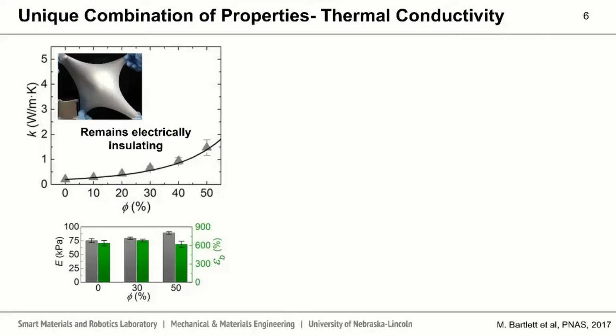This is important, especially if we talk about potentially thermally conductive elastomers. In some cases, we want these to be electrically insulating. Here is a graph that shows the thermal conductivity of these composites as a function of the volume loading of the liquid metal in the composite, and we see an increase as the loading of liquid metal increases from 0 to 50% by volume. One really unique aspect is we see a negligible change in its modulus as a function of loading all the way up to 50% while remaining very highly elastic, having strains up to 600% before break.